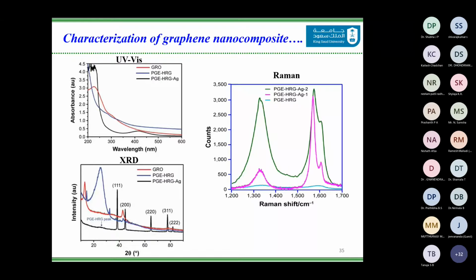Moving further, we did the XRD for the same, and we found that the highly reduced graphene gives us a signal at around 22.4, sorry, 26. And silver also was present in the XRD spectrum that we obtained. So you can say that we were successful in depositing silver on the surface of the graphene, and the crystalline nature of the silver is intact.